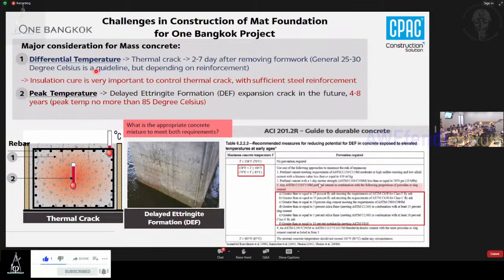Yeah, the first one is a differential temperature of the structure here. In general, the core of the concrete is going to give a high temperature, and the edge of the structure gives a lower temperature. So if there is differential temperature, the concrete can shrink and expand differently, which means there is potential to crack. That is a thermal crack. We have to be concerned about this because we have to put some rebar to control the crack around this area.